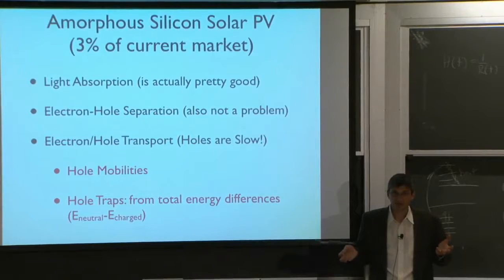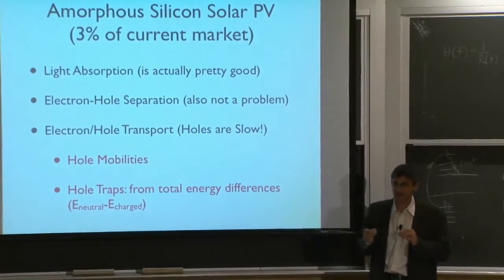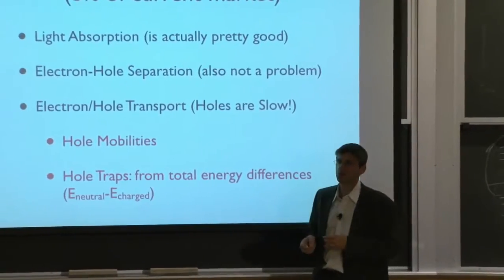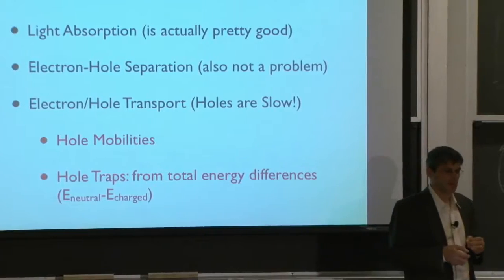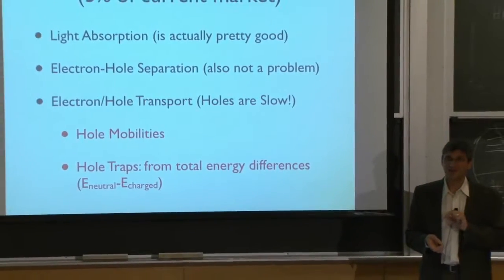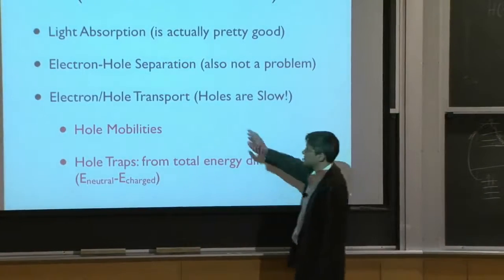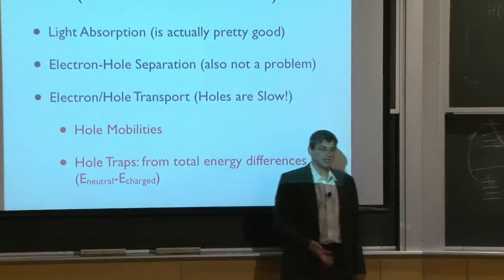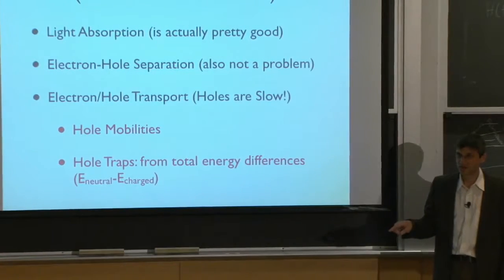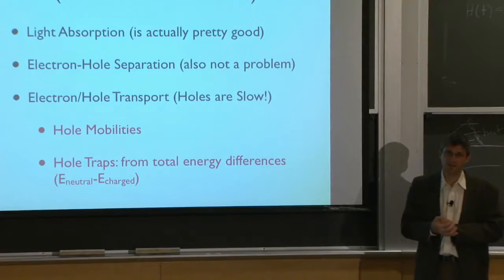It's a messy material. Now, there are still very important ways of doing the processing that can make a difference on the performance, right? Hydrogen concentration, how you anneal it, but it's a much easier material to make since it's inherently messy. Now, that poses a real challenge because you want to fix the transport of charges in a messy material. And it's really hard to characterize messy materials, right? Beautiful problem for computation.